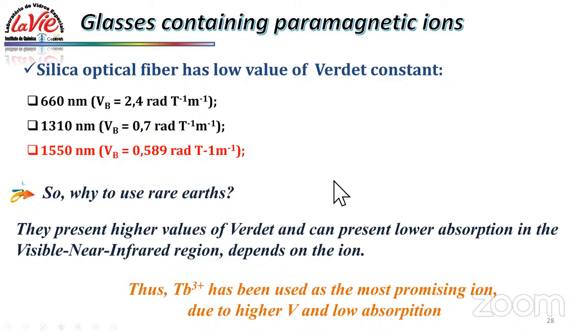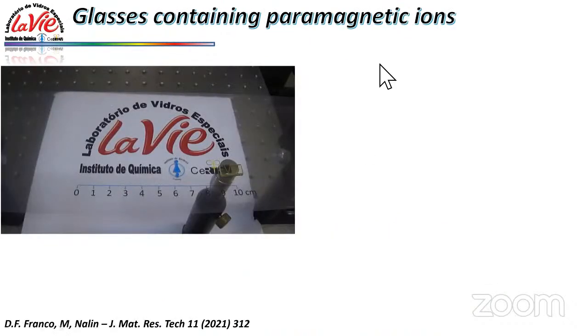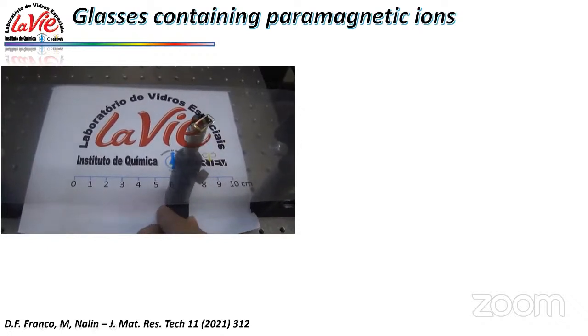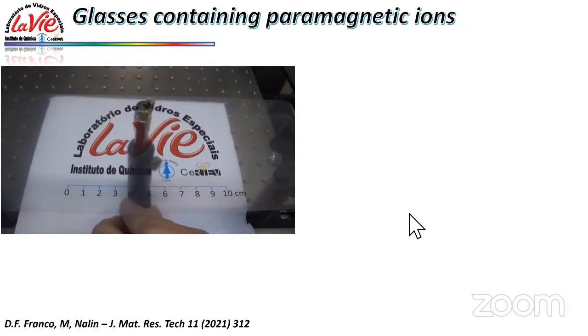When you ask why to use higher Verdet, as I told you before, we can use terbium, and it shows the most promising properties to increase the value of the Verdet in this kind of material. Even if the Verdet constant of silica is quite low compared to results that we find in the literature now, silica is used for these optical components, mainly in the infrared. So in this case, we move to compositions that work with terbium, and then they are also magnetic.